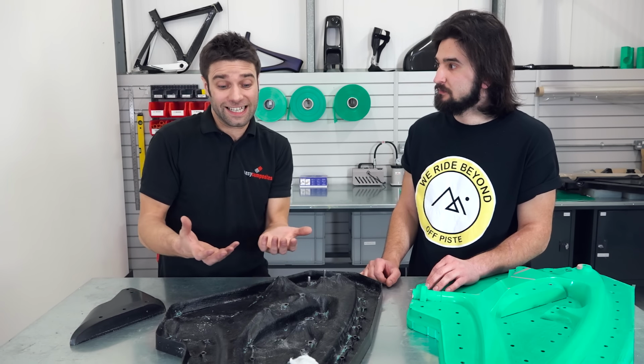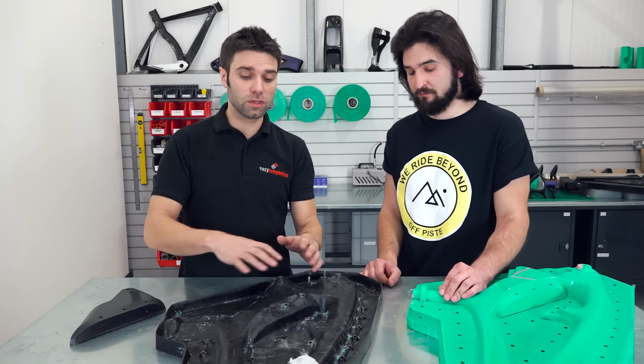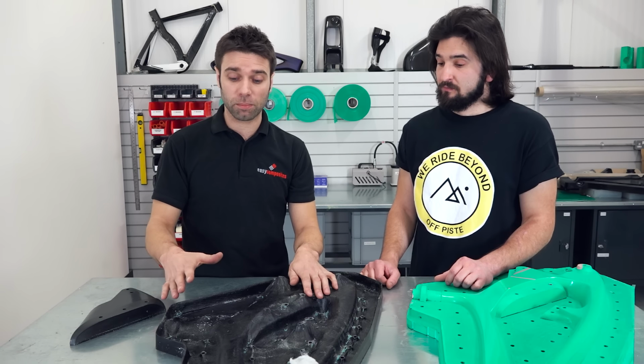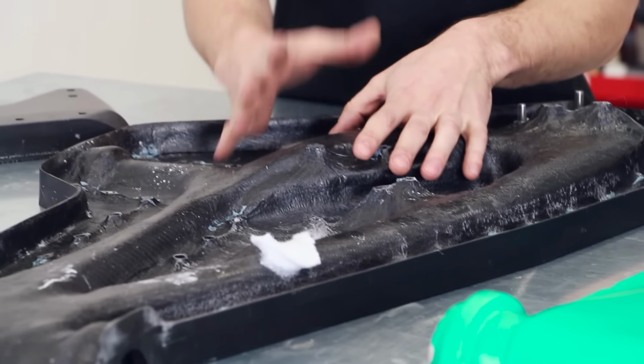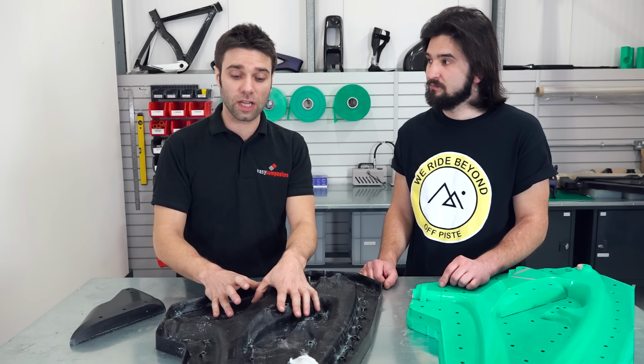Fully consolidated. Yeah. So the purpose of a debulk is basically pulling a vacuum, usually with a perforated peel ply. You pull a vacuum and it just compresses at each stage of your lamination. It takes the bulk out of the material. So where the material's normally sort of sagging away from the mould, by putting it into a vacuum bag, it presses it into the corners and really ensures a good layup.